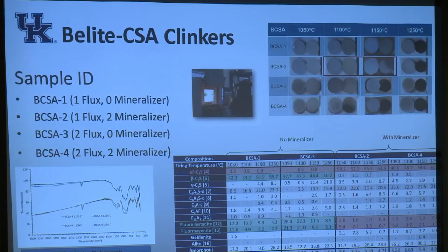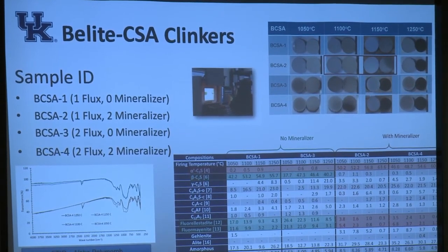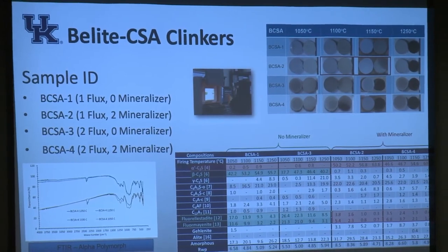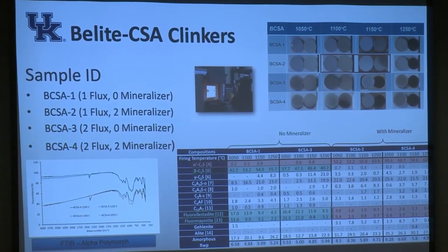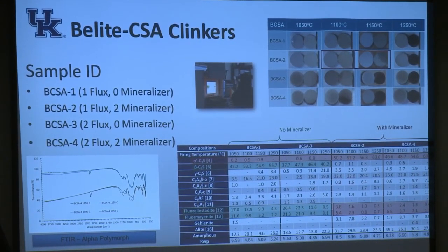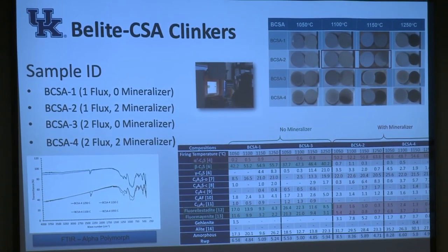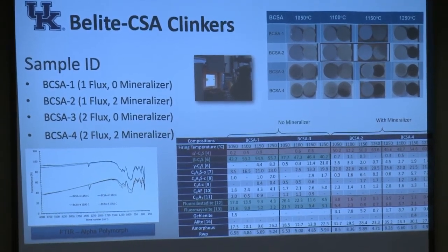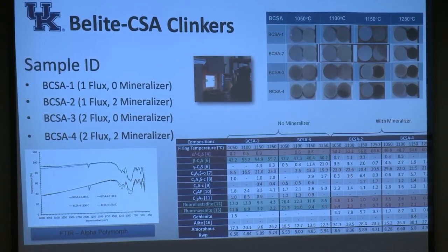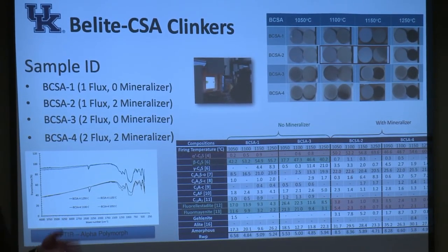So this is what you end up getting into. In our lab, we have a batch scale kiln, so we can run these small pellets to compare our predictive models to what is actually happening in the furnace. And then we have a pilot scale rotary kiln, so we can scale up and see if our models will exist at more of a production level, and then we get enough quantity to test out performance, okay? So Portland cement is typically heated at around 1450 degrees Celsius.